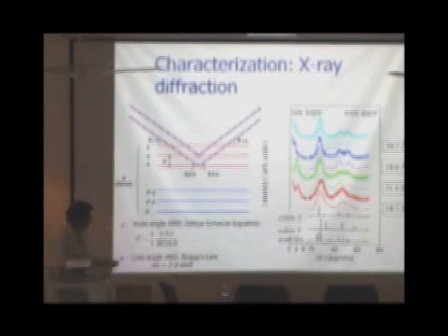The other thing is you can try to align these particles and form superstructures. If you form superstructures, then the X-rays will diffract between these particles, and you can get low angle peaks, which according to the Bragg equation would correspond to the ordering of these particles.